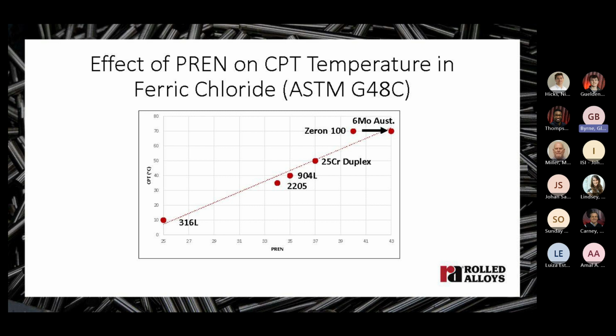Initially, the PREN equation was percent chrome plus 3.3 times percent moly. When new nitrogen-bearing alloys were developed with improved corrosion resistance, a term for nitrogen was added to the equation, and similarly when tungsten-bearing alloys became available. For example, Zeron 100, which contains between 0.5% and 1% of tungsten, moves to a better fit position against the regression equation when tungsten is utilized in the regression analysis and the PREN equation.